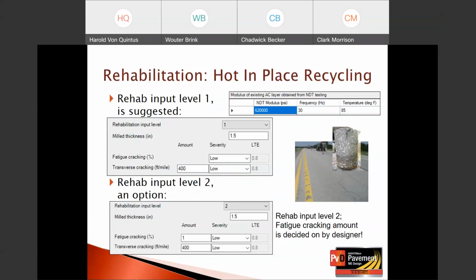Okay, so this is our simulation. So rehab input level 1. We're milling 1.5 inches, as shown in the middle box, for rehab level 1 is suggested. So the fatigue cracking amount is blank, because that's being determined by the program from the back calculated elastic layer moduli to define damage. The cracking is believed to be a low severity from the surface observations. Transverse cracking, we have 400 feet per mile that we see at the surface prior to the hot in place recycling, and those are of a low severity.